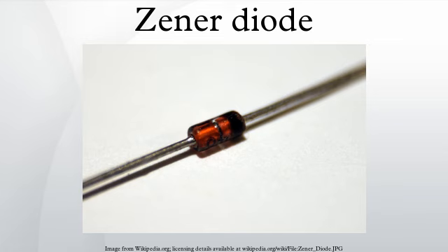Subsurface Zeners. A subsurface Zener diode, also called buried Zener, is a device similar to the surface Zener, but with the avalanche region located deeper in the structure, typically several micrometers below the oxide. The hot carriers then lose energy by collisions with the semiconductor lattice before reaching the oxide layer and cannot be trapped there. The Zener walkout phenomenon therefore does not occur here, and the buried Zeners have voltage constant over their entire lifetime. Most buried Zeners have breakdown voltage of 5–7 volts. Several different junction structures are used.